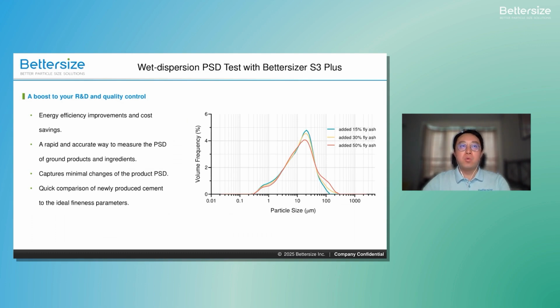Here is a real-world demonstration of how the Bettersizer S3 Plus helps with cement R&D and quality control. Let's focus on the graph on the right. We will start with a single, consistent base of ordinary Portland cement, OPC, and then created three distinct samples by adding different ratios of fly ash, 50%, 30%, and 15%. The Bettersizer S3 Plus easily resolves these three separate and distinct particle size distribution curves, one for each mix ratio.